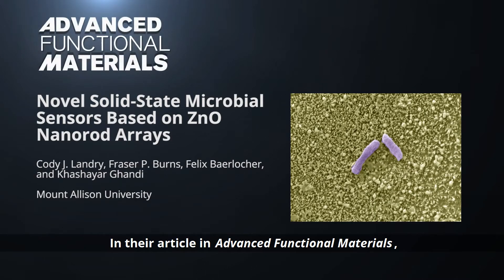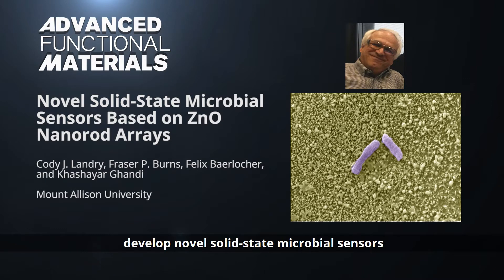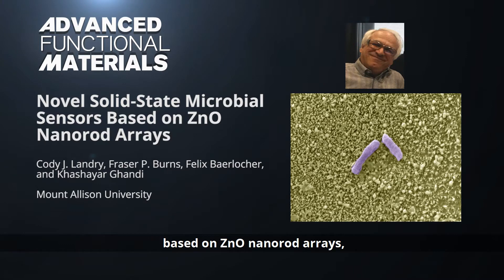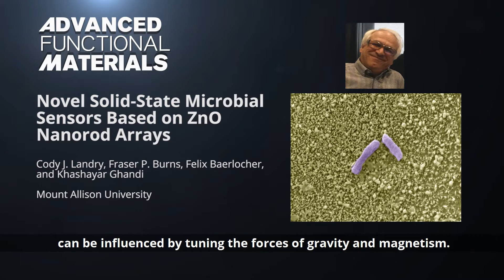In their article in Advanced Functional Materials, Dr. Khashayar Ghandi and colleagues from Mount Allison University, Canada, developed novel solid-state microbial sensors based on zinc oxide nano-rod arrays, and showed that the size, shape, and order of the nano-rods can be influenced by tuning the forces of gravity and magnetism.